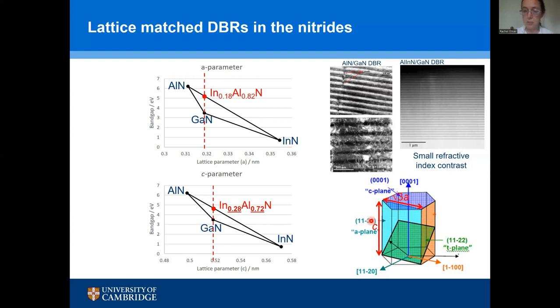That has some advantages in terms of how the devices operate, but it now means we also have to worry about a second lattice constant, about the spacing of atoms along this direction I've got labeled as C. Now, the trouble is that I can also make lattice matched indium aluminium nitride to gallium nitride along the C direction. And I would do that by having 28% indium in my alloy. But what I can't have is lattice matching along both C and A simultaneously, because I can't grow in my crystal growth system material that has both 18% and 28% indium. That's not possible. It has to be one or the other.